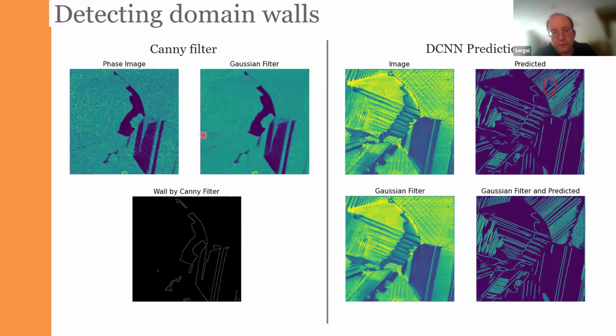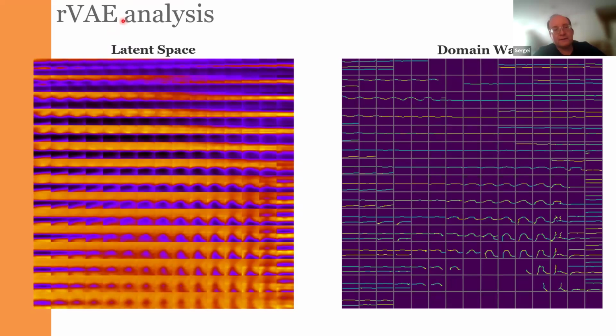Well, the first step is to find the domain walls. It's usually a much better start than just using the rectangular grid sampling. Finding 180-degree domain walls is straightforward. They can be found just by Canny filter and give a very good image. Finding the non-180-degree domain walls is more complicated, so that required building the ResNet-type of architecture, but that can also be done. And once we do that, we can take this data set and put it in the autoencoder.